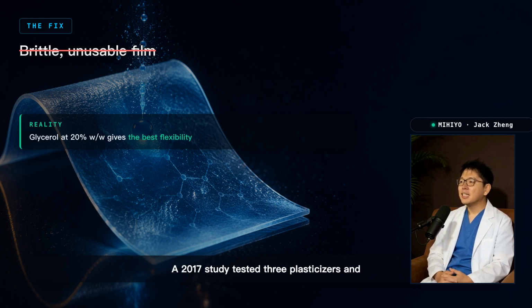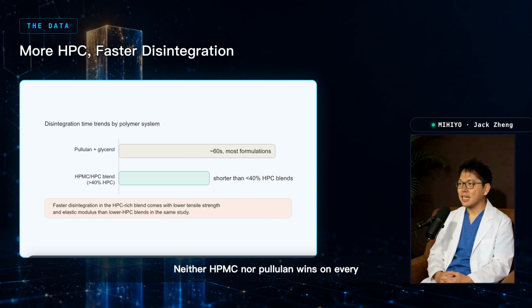A 2017 study tested 3 plasticizers and found glycerol at 20% by weight gave the best flexibility, and most films still disintegrated within a minute. The plasticizer isn't cosmetic, it's what keeps the strip from snapping in your pocket. Neither HPMC nor pullulan wins on every axis alone.